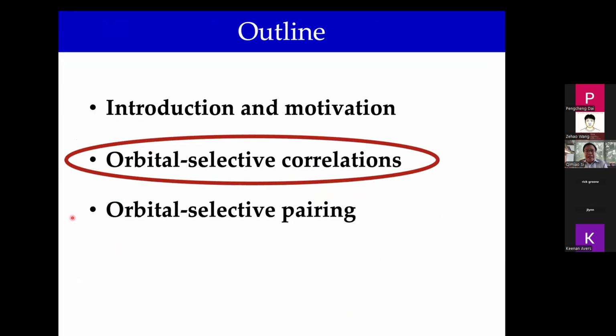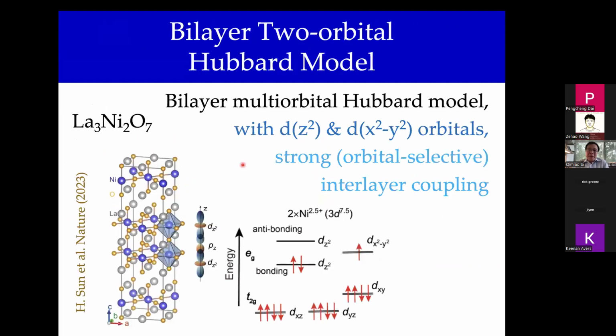So this guided our thinking, and we decided to take seriously these multi-orbital models, putting in the Hubbard and Hund's interactions, and ask what kind of perspective we should take about the correlations in some detail. So one of the features that's important to this bilayer nickelate is that if we involve the two orbitals I mentioned, the 3d z square orbital and the 3d x square minus y square orbitals, the z square orbital has the geometry such that the interlayer coupling is expected to be stronger than for the 3d x square minus y square orbitals.